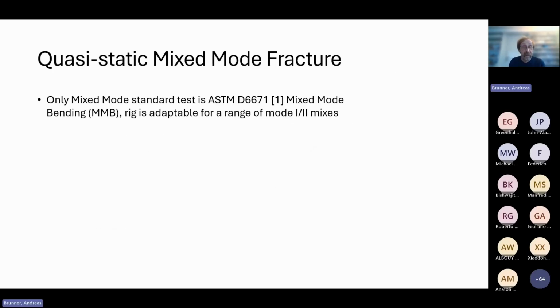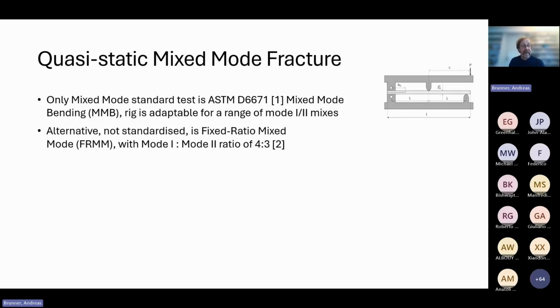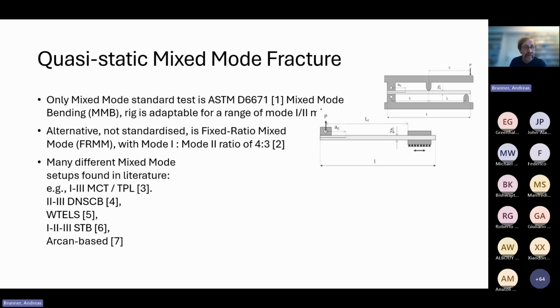Okay, this has all been explained before. So there's this ASTM mixed mode bending test, the similar setup that Yentl showed before. There is an alternative, which is called a fixed ratio mixed mode 1-2 test. And this is not standardized, but within ESIS-TC4 we're working on standardization of that. The big advantage of this test is that the mode mixity is clear. There's no argument that this test yields a mode 1 to mode 2 ratio of 4:3, whereas in other tests, sometimes it's not quite clear what the effective mode ratio is.